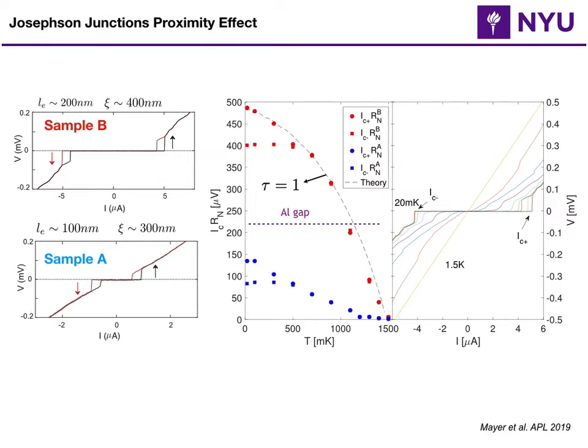And in this paper, we go through it in great detail. You can be in the short ballistic, you can be in the diffusive, you can be in the long junction limit, right? And that changes the supercurrent or ICRN values that you get. If you plot ICRN as a function of temperature, you see that the Tcs are almost the same, both around 1.5 Kelvin. But for sample A, which had lower quality, the ICRN at the lowest temperature reaches about 150 microvolts, while the red data points, which come from sample B, reach up to 500 microvolts.